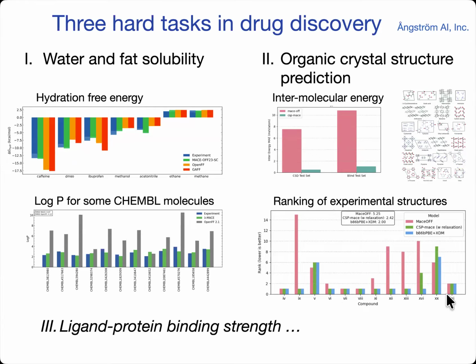And these are the blind test compounds. And you can see that with the MACE model that's specifically made for crystal structure prediction, you almost recover the accuracy, except for 1 or 2 places, of what DFT would give for the ranking, where rank 1 means that you get the lowest energy structure equal to the experimentally seen structure.